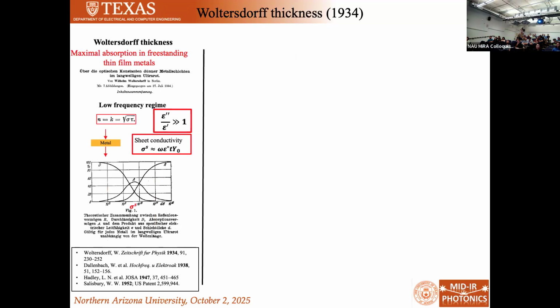So it turns out that people have been looking at how to absorb light efficiently in thin layers for many years, not surprisingly going back to radar times, when people were really pushing on radar. There's this Woltersdorf thickness, where Woltersdorf calculated exactly how thick a layer of metal had to be to absorb the maximal amount of radiation if it was just floating in space. It turns out the most you can absorb is 50%.